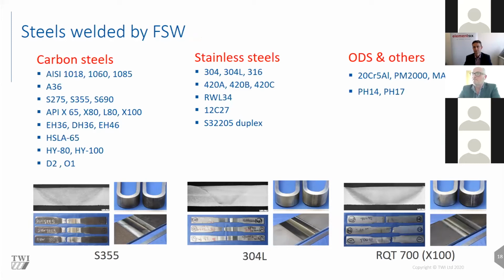When we first started welding, we started with just simple plain carbon steel, such as AISI 1018, 1060, which are just iron and carbon. We then gradually worked our way through the alloy compositions. So we started looking at structural steel, such as S355, some of these steels that are used in the oil and gas industry, such as the API X65 series, shipbuilding steels, such as DH36, HSLA 65, and all the time we're gradually moving up in alloy and carbon content until such time as we reach things like D2 and O1, which many people would suggest are very difficult or even impossible to weld by conventional means. We don't find that problem with friction stir welding.